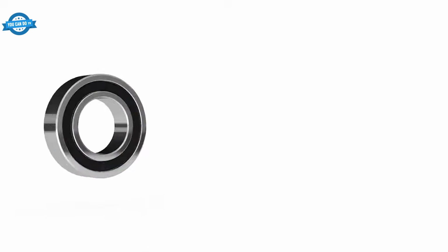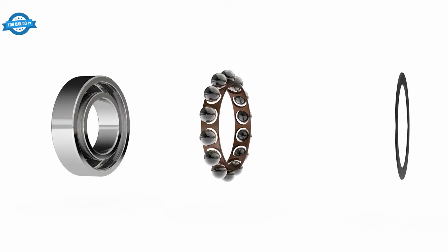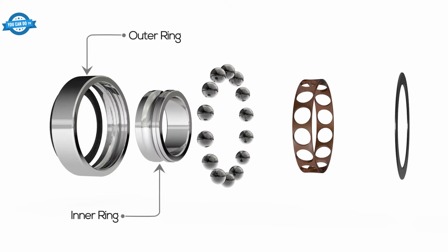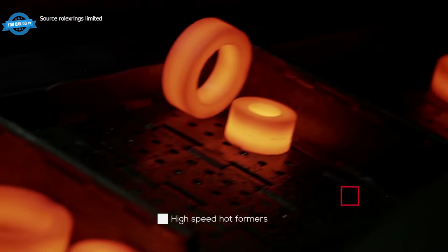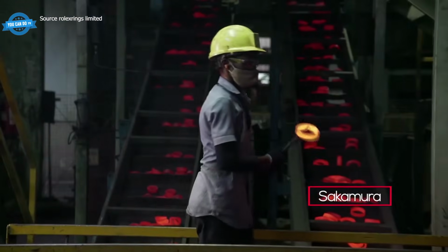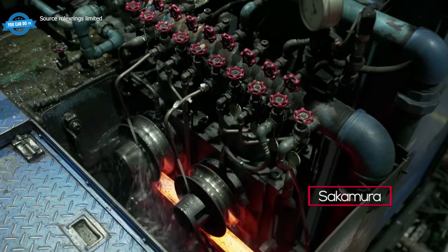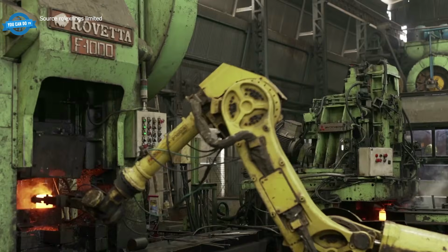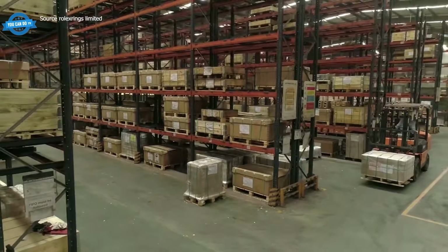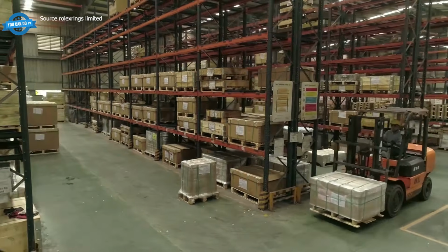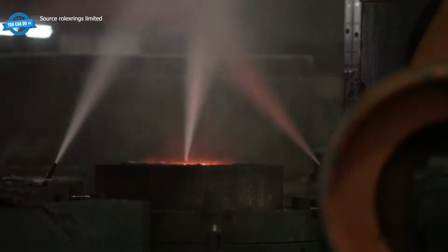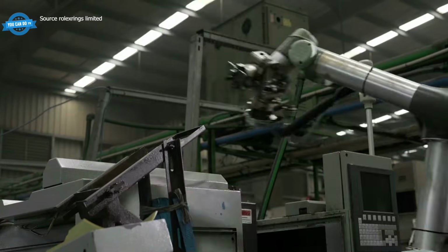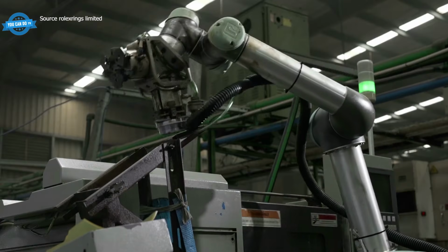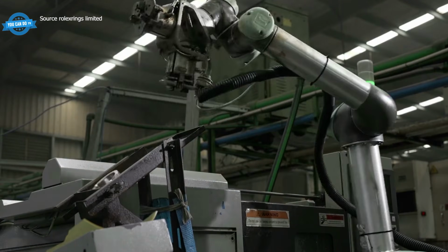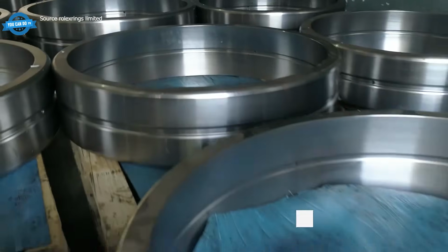Forged rolled rings solve this because ring rolling creates a continuous grain flow around the circumference. There is no seam, no weld, no starting point of weakness. Whatever direction the load comes from, the material has grain going the right way to handle it. The finished rings then get turned, ground, and inspected on CMMs that measure to a few microns. What you see leaving the factory looks like polished sculpture. What matters is invisible, sitting inside the crystal structure.